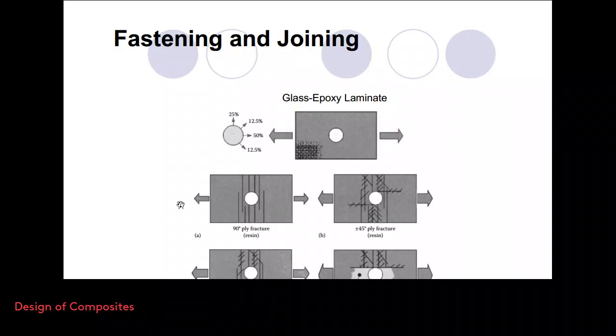In fact, we may have different types of failure. Generally we have a laminate with fibers which have different orientations, and commonly 0 degrees, 90 degrees, positive 45 and minus 45 degrees laminates apply, in fact. So we may have vertical failure lines, so cracks on the surface. This basically means that we have the failure in the matrix. So the 90-degree ply fails. So the load bearing capability of the 90-degree ply is not sufficient. So this basically means that we need to add some more 90-degree ply, increase the thickness.